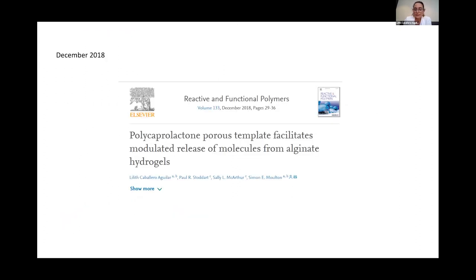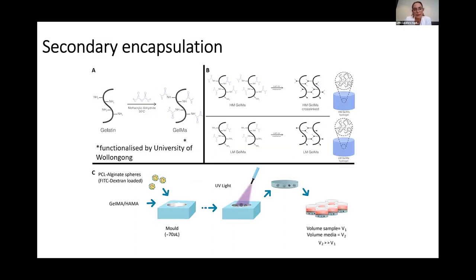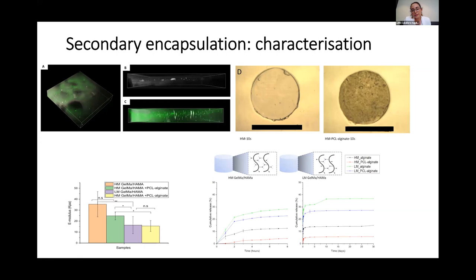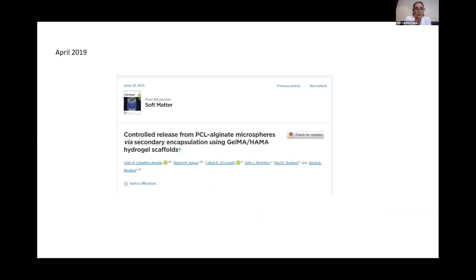And we investigated a couple of molecules of different molecular weight, and we published some of this work in December 2018. And then after forming these microparticles, we investigated what would happen if we embedded these microparticles within GelMA hydrogels. So what we call secondary encapsulation. And we utilized a highly methacrylated hydrogel, and compared that against a low methacrylated hydrogel. We did the characterization of this, and we also looked at the change in release profiles. And what we observed was a very, very slow release profile up to 30 days. So we published this work in April 2019 in Soft Matter.